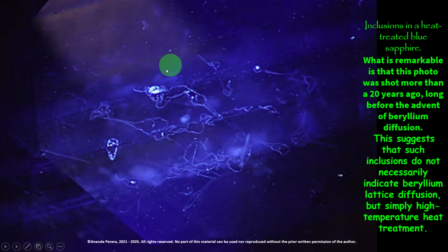Inclusions in the heat treated blue sapphire is this. This is heat treated blue sapphire. What is remarkable is that this photo was shot more than 20 years ago, long before the advent of beryllium diffusion. This photo comes from a heat-treated stone. This suggests that such inclusions do not necessarily indicate beryllium diffusion, but simply high temperature heat treatment. This is high temperature heat treatment inclusions, not beryllium inclusions, because it was taken 20 years before the advent of beryllium diffusion.